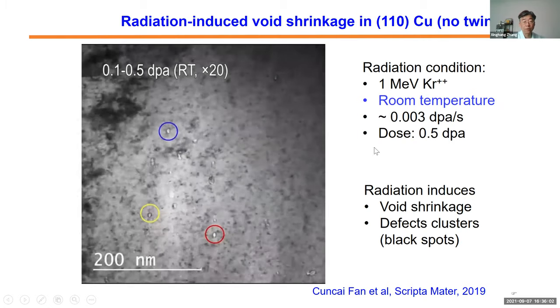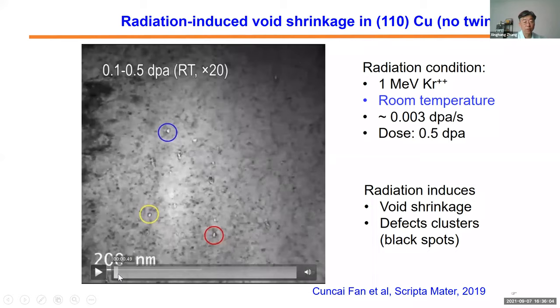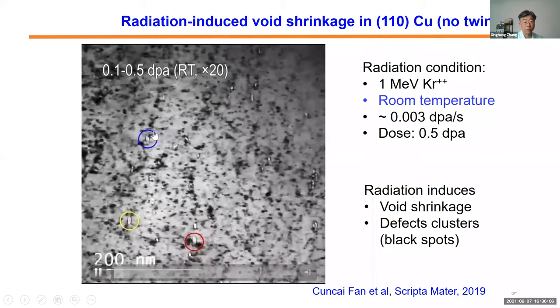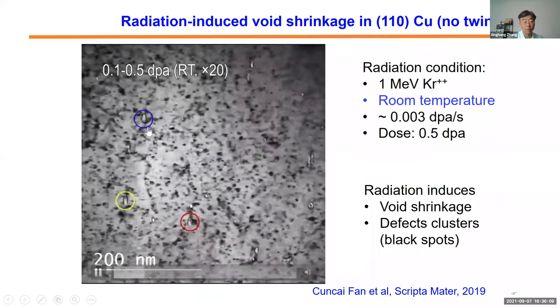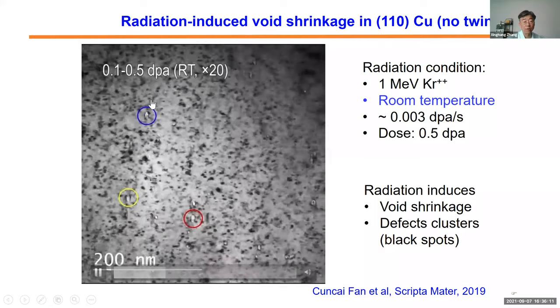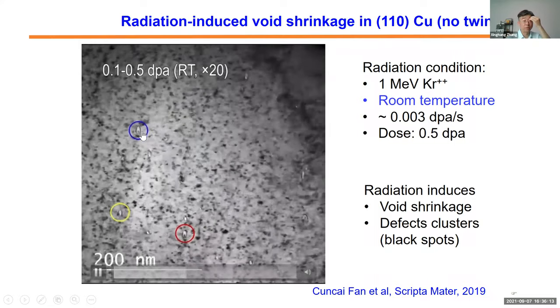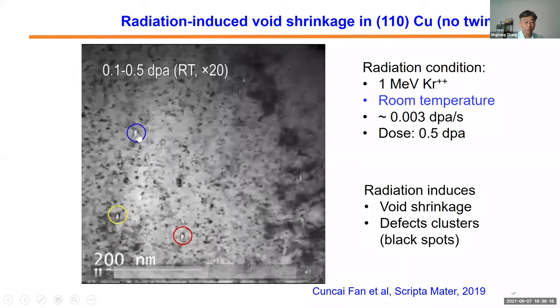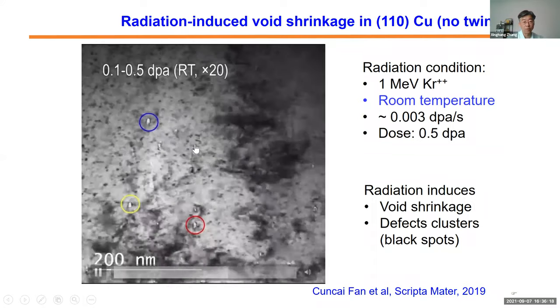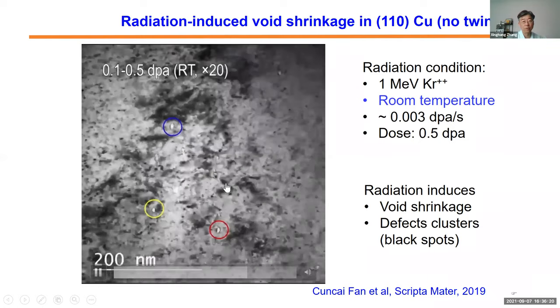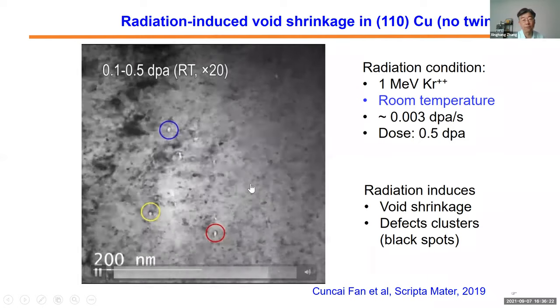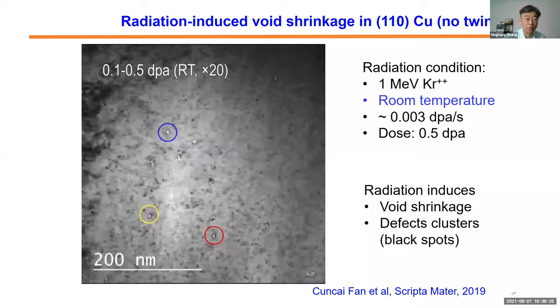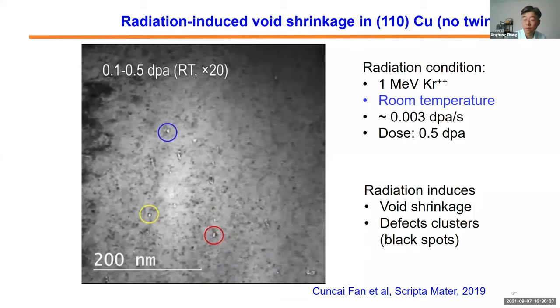So again, this is quite interesting because now there are no twin boundaries. Let me show this one more time. So you see that, remember the initial void size, and after you radiate this to about 0.5 dpa, a matter of maybe 10 or 15 minutes, everybody reduced their size. And of course, all these black dots are radiation-induced defect clusters, either vacancy loops or interstitial loops. But this void shrinkage phenomenon was confirmed again without twin boundaries. So how do we explain this phenomenon now?